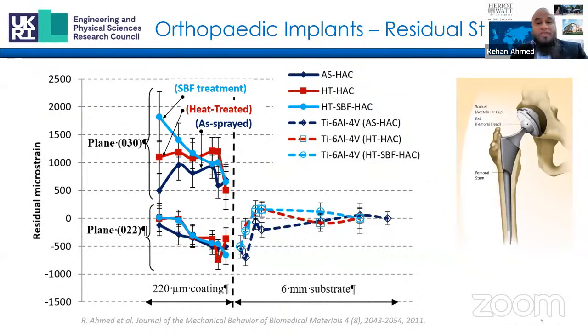So before I actually dive into that, I just want to classify how we actually experimentally measure residual stress. And experimental techniques adopted to measure residual stress can be broadly classified into three main categories. The first ones are non-destructive, and these are the techniques such as neutron diffraction, synchrotrons, and X-ray diffraction. And Raman spectroscopy also comes in this category. Then we have the semi-destructive techniques such as hole drilling, diametral compression, and layer removal or modified layer removal. And then finally, we have the destructive techniques such as sectioning and contouring. And there are some in situ techniques such as the curvature method in which you can actually get an idea of the residual stress profile of the coating.